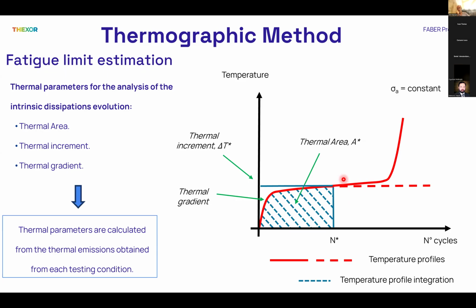But Mohsen and I will discuss this in the next slides. Very short time is how many cycles, please? If I get it right. Sorry? How many cycles did you set? You should use a short profile. In our experimental activity, we used 150,000 fatigue cycles for detecting the thermal parameters evolution. That's quite a long history.